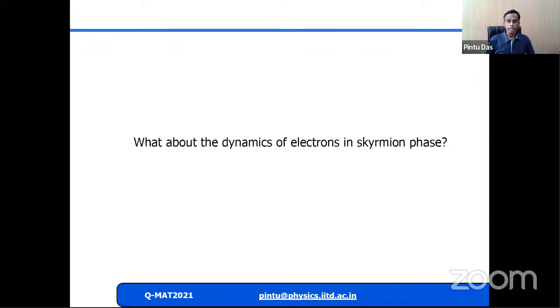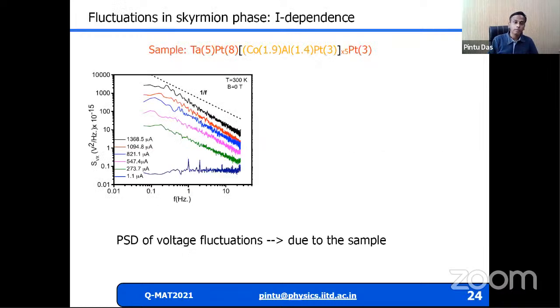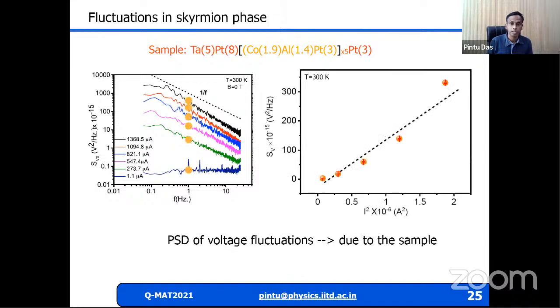Now, after we saw that, we are interested in looking at the dynamics of the electrons in this skyrmion phase. So for the dynamics, we have performed noise measurements. Typically, this is what we do. These are the power spectral density of the fluctuations in the voltage, the longitudinal voltage, or the longitudinal resistance. Sorry, this is not the skyrmion phase. This is at zero field, and we check this as a function of current to make sure that this noise is coming from the sample.